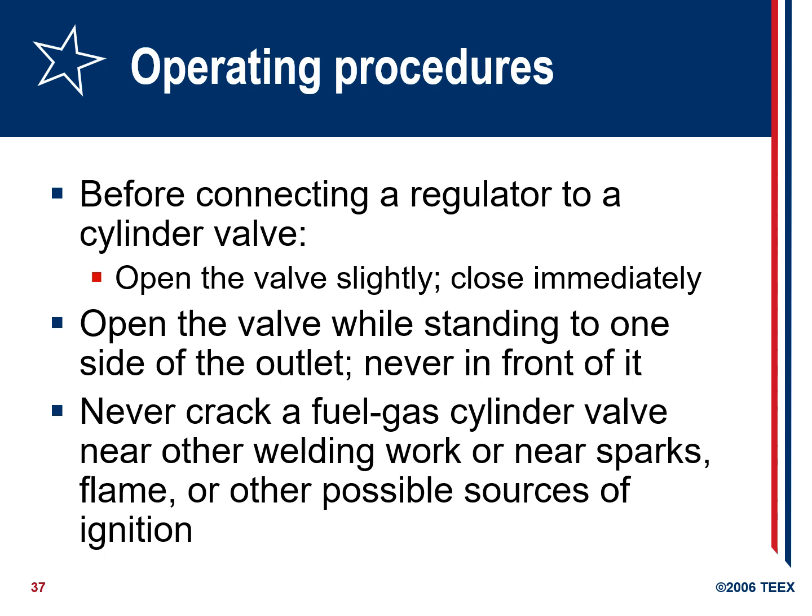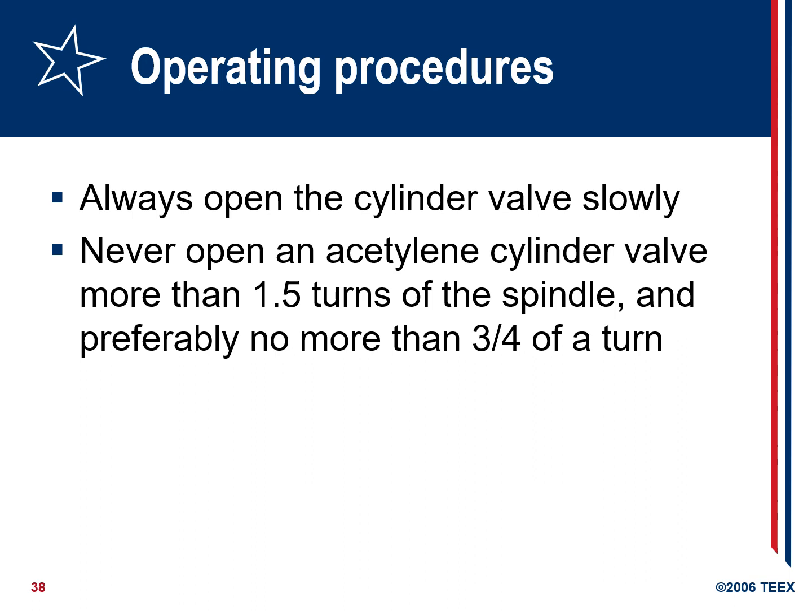Before connecting a regulator to a cylinder valve, open the valve slightly then close it immediately. Open the valve while standing to one side of the outlet, never in front of it. Never crack a fuel gas cylinder valve near other welding work or near sparks, flames, or other possible sources of ignition. Always open the cylinder valve slowly. Never open an acetylene cylinder valve more than 1.5 turns of the spindle, and preferably no more than 3/4 of a turn.